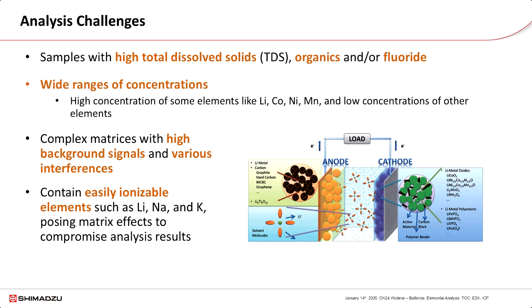For example, samples usually have very high total dissolved solids. Sometimes they have organics, they have fluoride. The elements in the battery samples have a very wide range of concentration. You might see high concentrations of lithium, cobalt, nickel, manganese, and low concentrations of other elements. The samples usually have very complex matrices with high background signals and various interferences. They also contain easily ionizable elements such as lithium, potassium, and sodium. All those different factors can affect the accuracy and precision of analysis results.